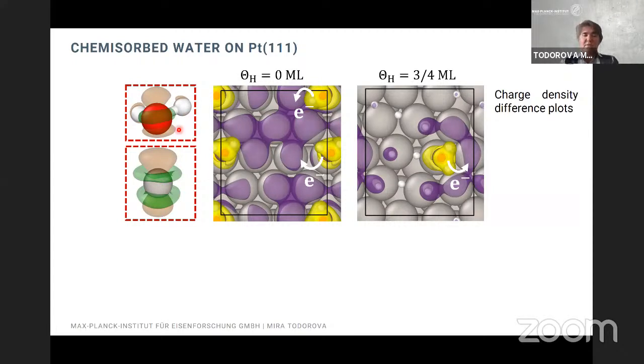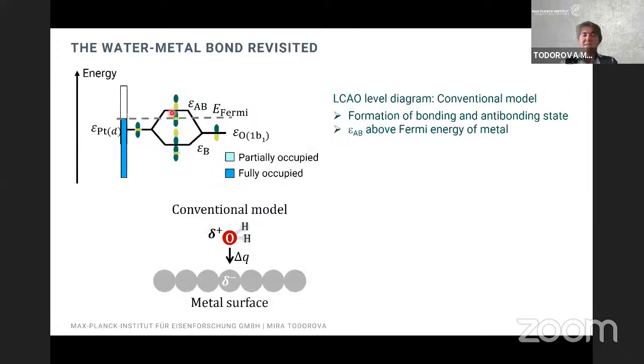The conventional picture that we have, so this kind of arrangement has been discussed before, is that there is an interaction between the water 1b1 level and the platinum d states, which leads to the formation of a bonding and an antibonding state. And this is a picture that is known from the literature. However, the conventional model assumes that the Fermi energy is between the bonding and the antibonding state. And so the charge transfer is directly from the water molecule to the platinum atom below it.